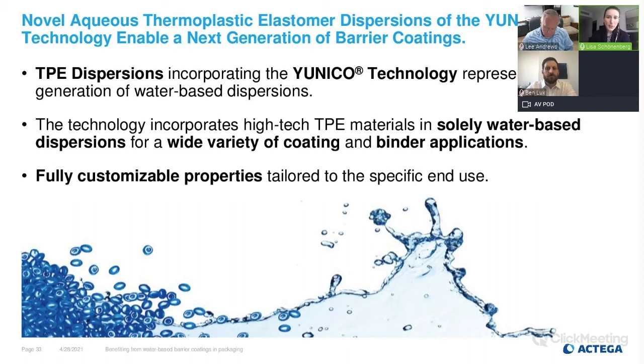With the help of the unique Yunico technology, polymers that are generally difficult to disperse can be incorporated in water without the use of dispersants or further additives. In conventional dispersions, these additives often render products unsuitable for the direct food contact. With the patented Yunico technology, it is possible to disperse high-tech TPEs in solely water-based dispersions. No questionable additives are needed.